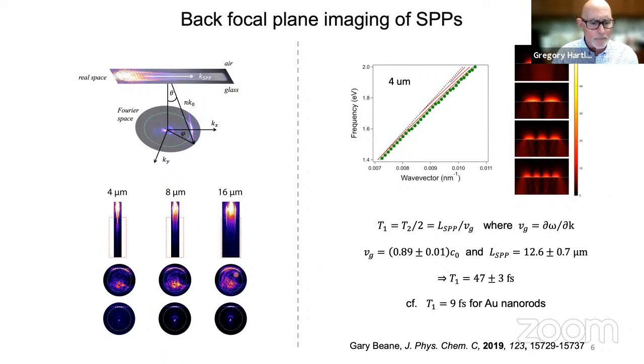Okay, and you can see there's a couple of wave vector diagrams here. If we collect light from the whole structure, we get these arcs again because the plasmons are moving off in different directions right at the start here. If we limit our collection to just this red triangle area here, lower down the wire, now everything's moving in the same direction and we get lines again. And either way, we can measure the wave vector.